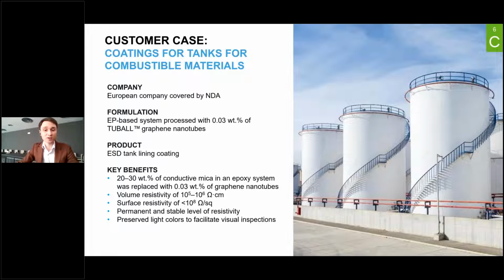Color is a huge advantage for this type of coatings for two reasons. First of all, many servicing companies today require tank lining coatings in two colors. For example, dark and light gray, or dark brown and light brown. You can ask me why. Because they can easier and more properly control the thickness of the coating during application. Just imagine the specialist of servicing company may apply black layer and then light one, and in the areas where there is a contrast between them, specialist very quickly recognizes not appropriate thickness of the layers, and it helps to save a lot of time during application.